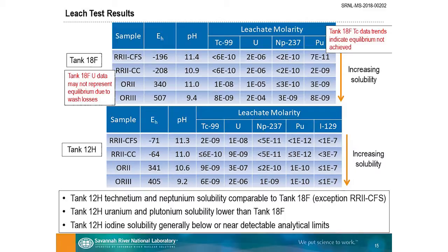Tank 12 results are shown on the bottom. We did not reach the same range of EH for these samples. We did drive the samples to near the pH targets that we were trying to, but as I said, we struggled to maintain them there continually. So in general, technetium and neptunium solubility is comparable for tank 18 and tank 12. Uranium and plutonium solubility was lower for tank 12 than tank 18. They were happy to see that, the folks in closure. Iodine solubility is generally below or near detectable analytical limits.